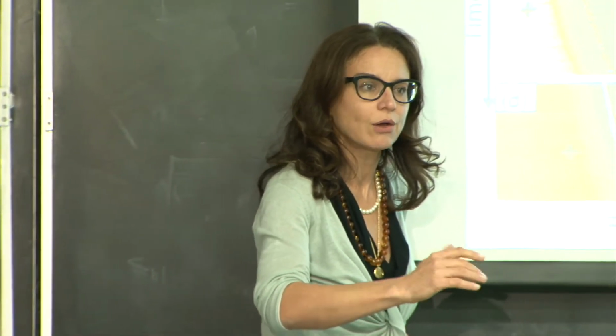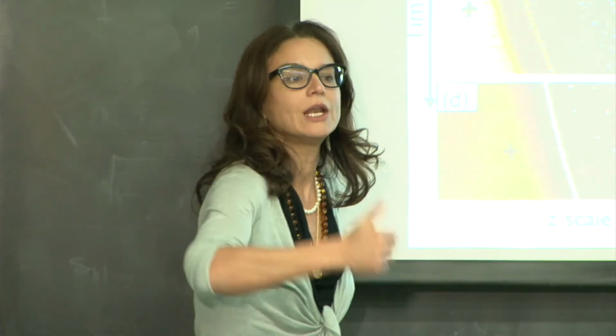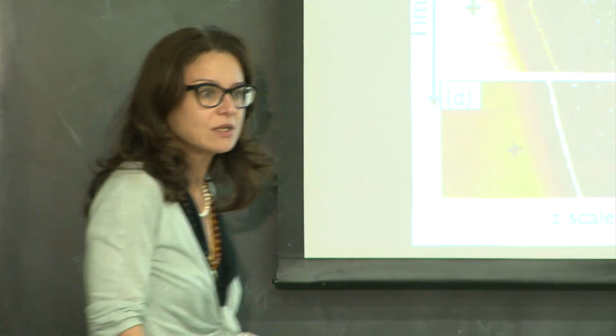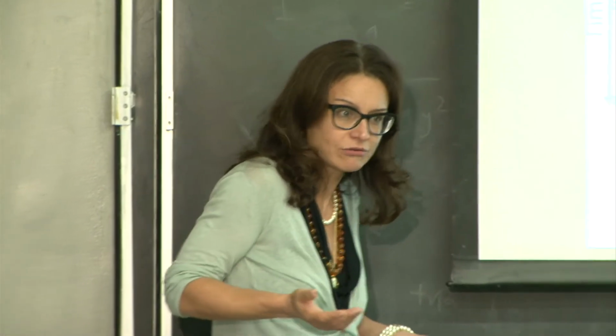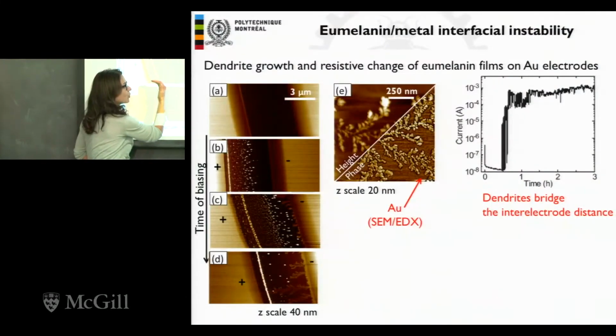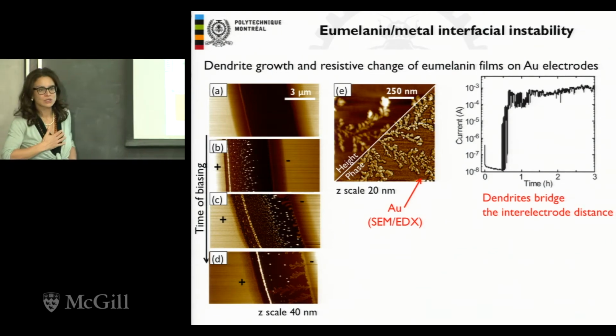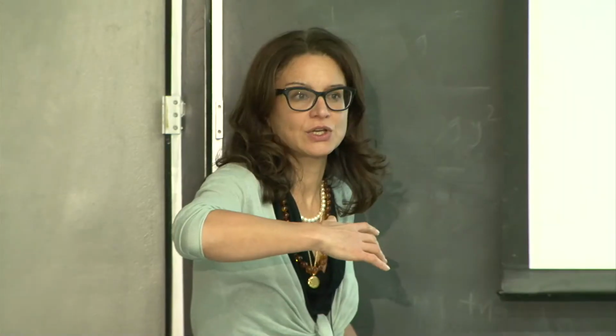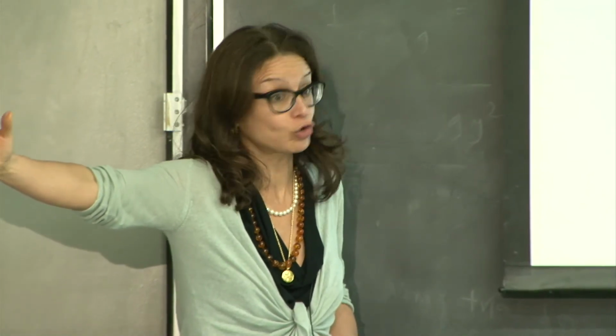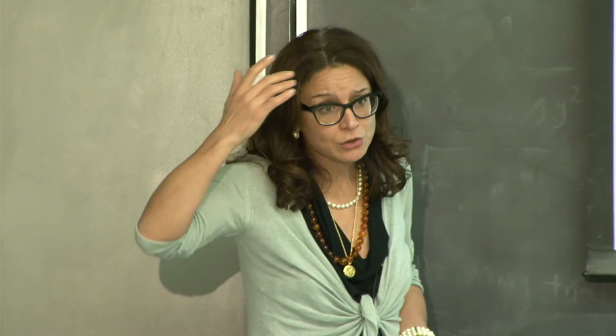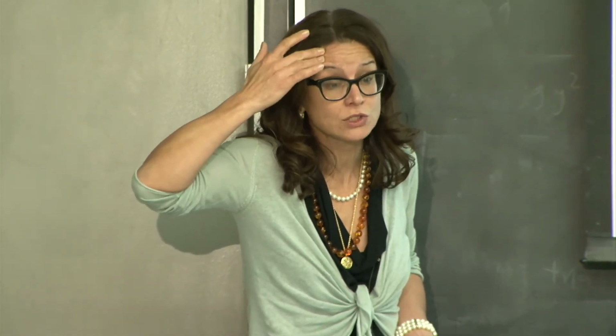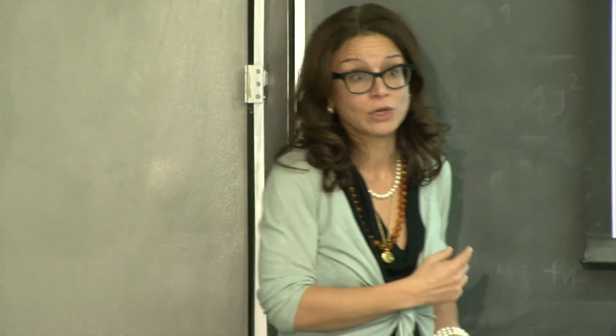Okay, so the first thing, we dissolved completely our electrodes, of course. The chloride formed complexes with our gold, chelation properties of our melanin. Chloride is present because melanin has been extracted from a sea medium, it's the black ink of the cuttlefish at the end of the day. So we formed really dendrites bridging the two electrodes within minutes. So if we don't want, as physicists or physical chemists, to have confusing or misleading or totally wrong interpretation of our experimental results on the charge carrier transport properties of biomaterials, better to think about the chemical composition in terms of salts beside the organic material before doing the experiments.